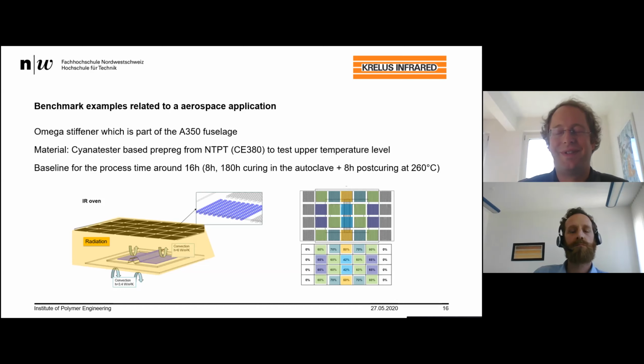So it's a high-level thermoset material with a glass transition up to 400 degrees. Normally used up to operation temperatures nearly to 300 degrees. So, for instance, for a turbine or so on. And this material normally has to be cured around 260 degrees.